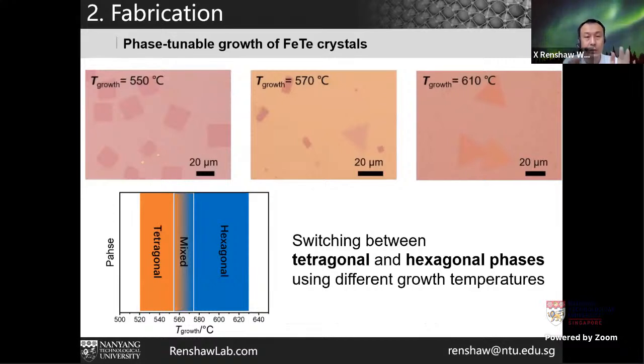As you can see, these are the optical images of the product. If we have a low temperature growth, for example 550 degrees C, you can see square crystals, or small square flakes, on top of the substrate. And if we go to the higher temperature side, you get the triangle-shaped hexagonal phase. In between, of course, we will get some mixed phases. So we have a small phase diagram: if we change the temperature, we can get different phases.